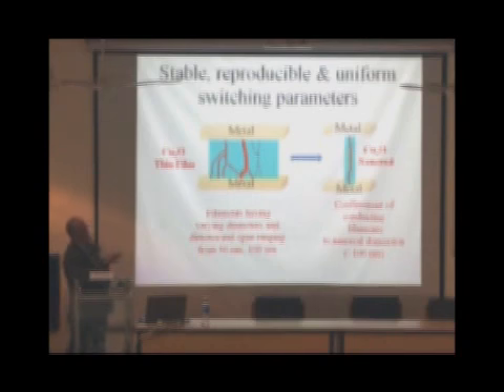When you have each element consisting of one nanorod or a finite number of nanorods, each filament will be formed inside the diameter of the nanorods. So, in the present case, we have diameters of around 100 nanometers. If you reduce this diameter further, you have a very small dimension in which the filament can form. And thus, by controlling the diameter of the nanorod, we are controlling the lateral extent to which this filament can grow. And this can be one of the methods by which we can improve the cell-to-cell uniformity of the device.